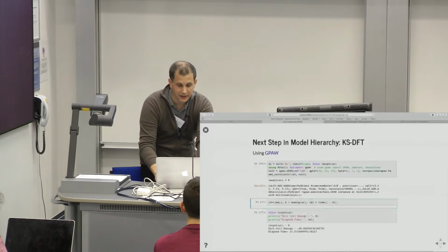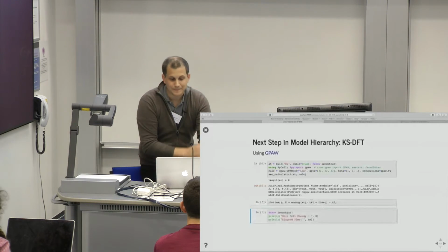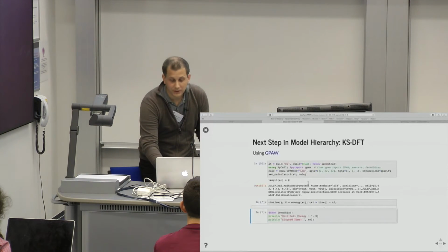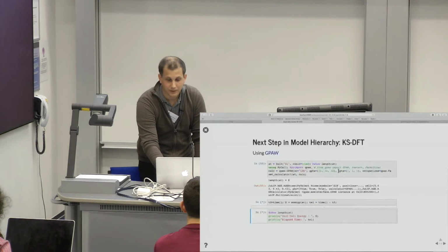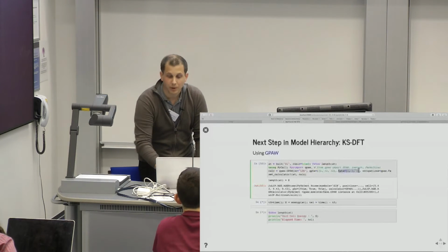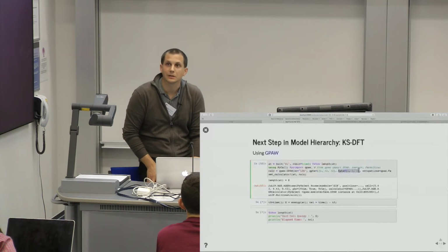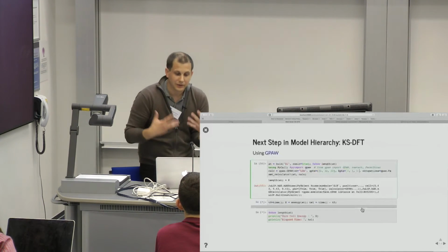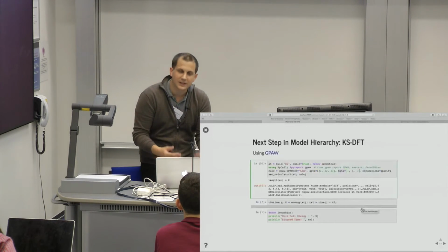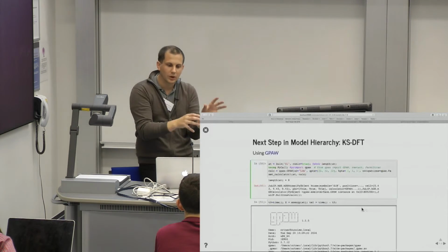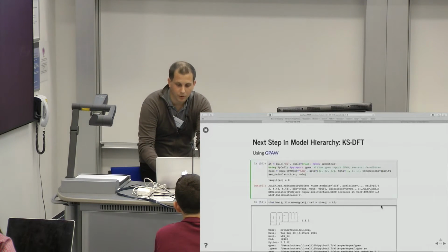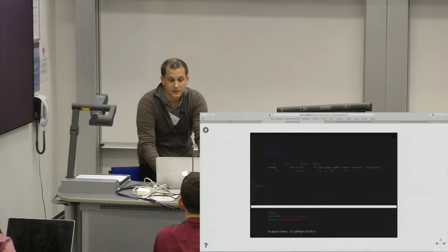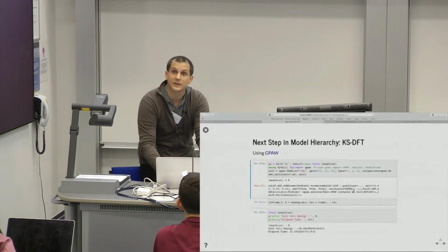And if I now evaluate the energy, wait a minute, for just 8 atoms. And I'm doing this, so if you know anything about electronic structure, the number of K points I'm using is essentially illegal. You're not allowed to do that. It should be much more costly than that. So the cost of these codes just explodes. And this is why I use this hierarchy of tiny toy models and then slowly go up to more and more sophisticated models to try out what really happens. So yeah, it's 22 seconds to just evaluate the energy of a single unit cell.